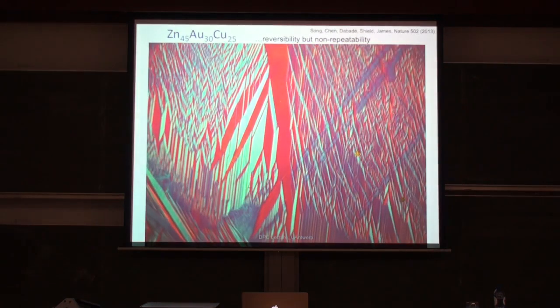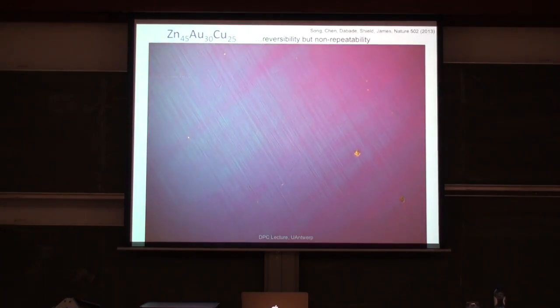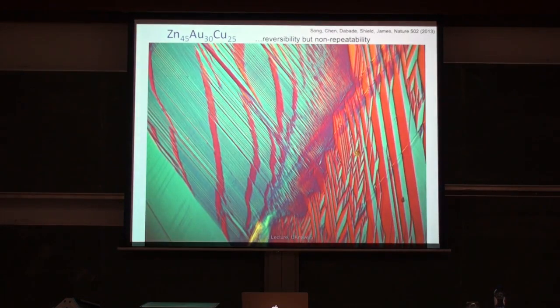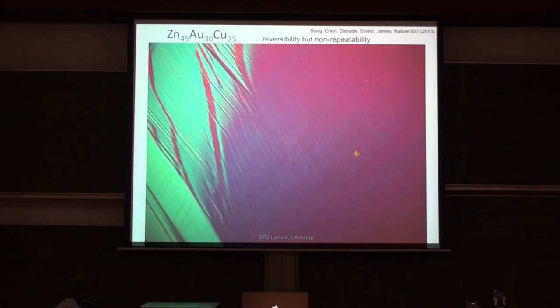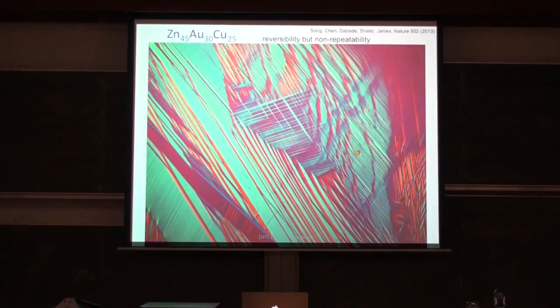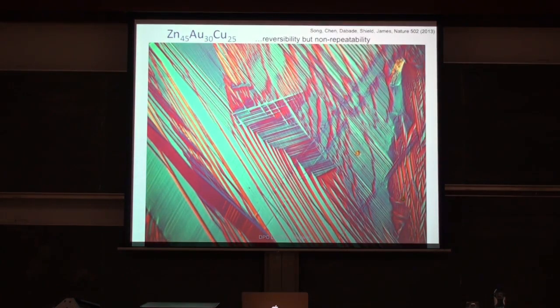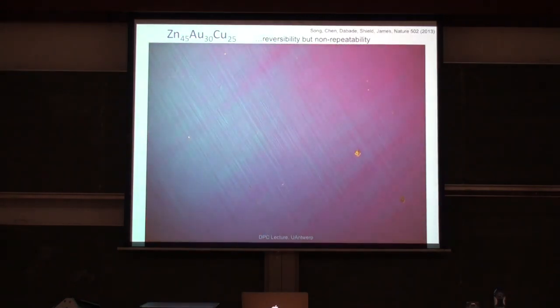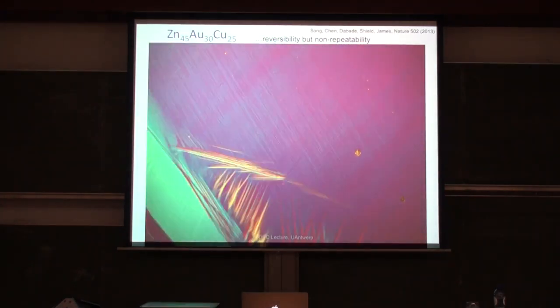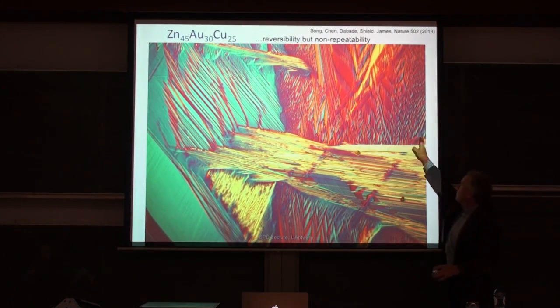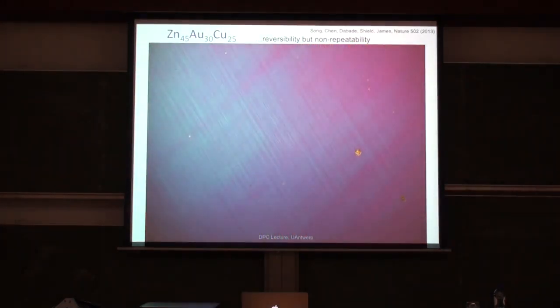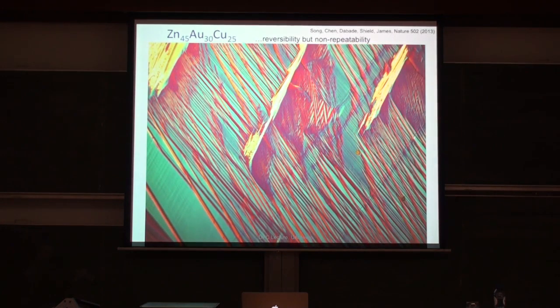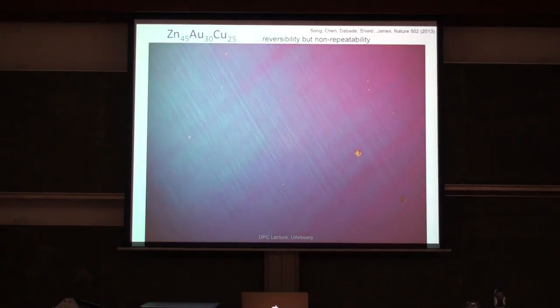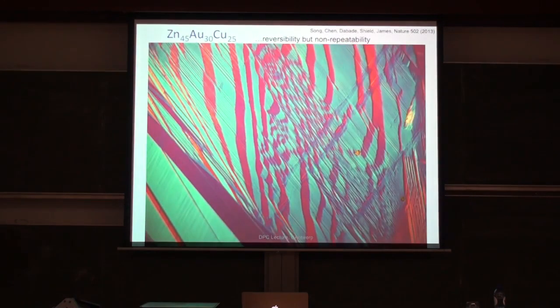But if you're familiar a bit with these, you would see lots of unusual things in this picture. First of all, if you look carefully, you can see some curved interfaces, so it's kind of what you expect. Every picture is different. So that's heating and cooling. That's the martensite phase, that's the austenite phase. The different colors here correspond to the different variants of martensite. And this material has 12 variants of martensite. So it's quite unusual microstructure and quite unusual dynamics for a phase transformation.